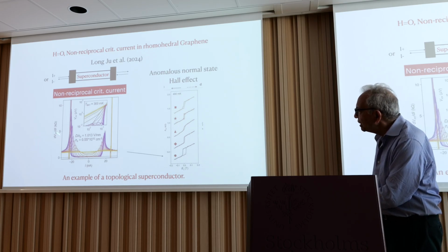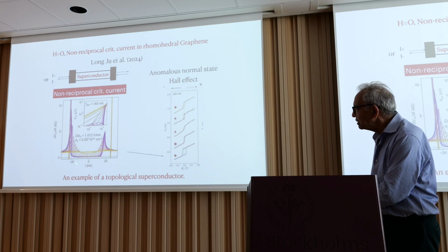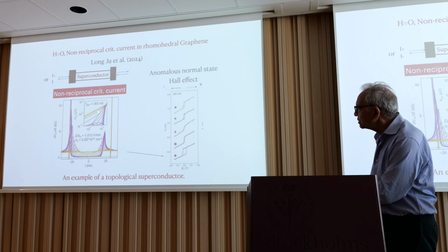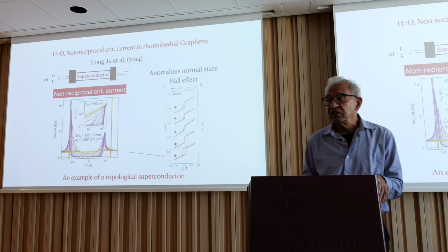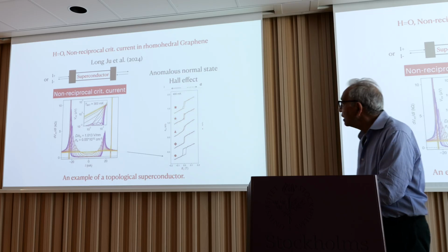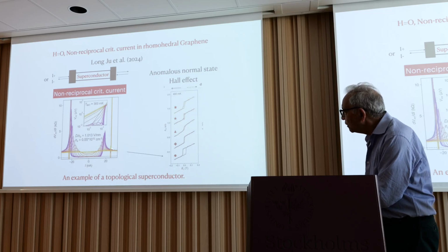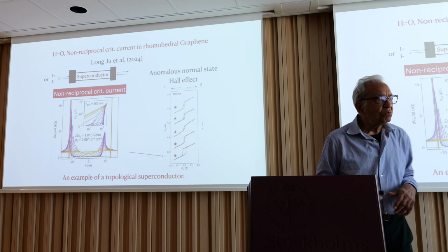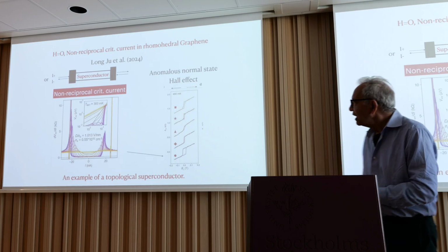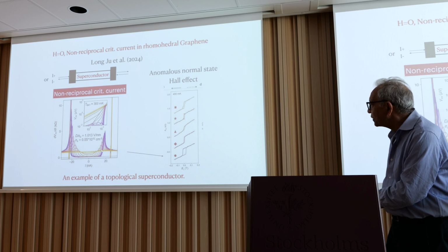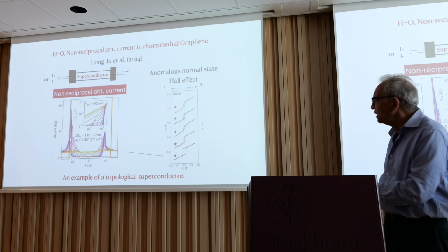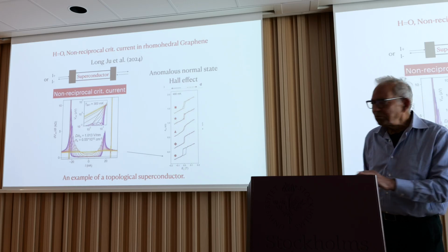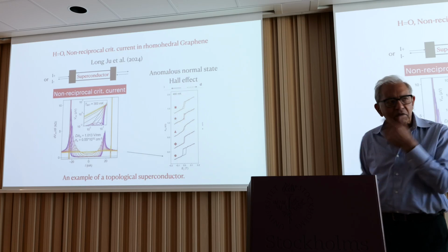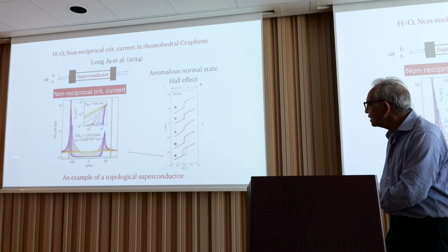But you see here, this gentleman has plotted for you derivative of the voltage with respect to current versus current at various temperatures below the transition temperature of about 300 millikelvin, and there systematically you will observe that the critical current in one direction is quite different from the critical current in the other direction. In this compound, when he goes above Tc, and he has measured it in various different samples, this is the cleanest example of his non-reciprocal critical current.